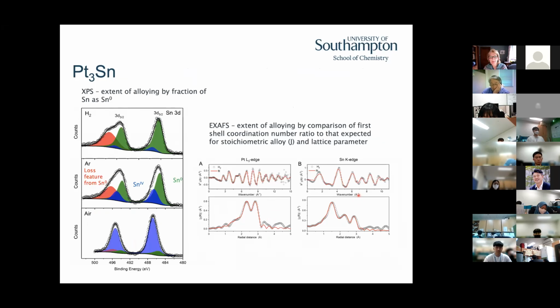We looked with XPS, and XPS is a little bit more surface sensitive, but when you're talking about nanoparticles, it's not completely surface sensitive. It allows you to see that we are indeed changing the oxidation state of the tin as we change the alloying. So in air, argon, and hydrogen, the air is a really poorly alloyed material. The tin is mostly present as tin oxide, and the hydrogen is a very well alloyed material where the atoms are really mixed.